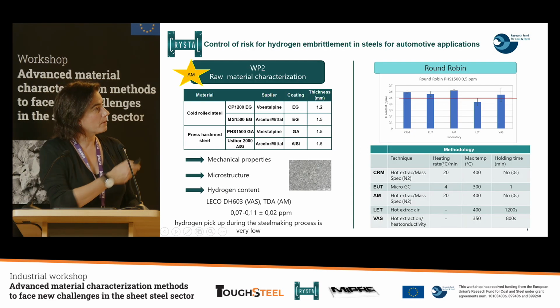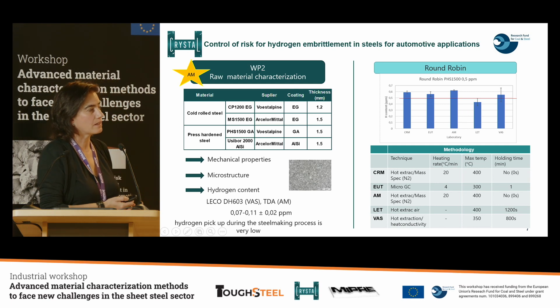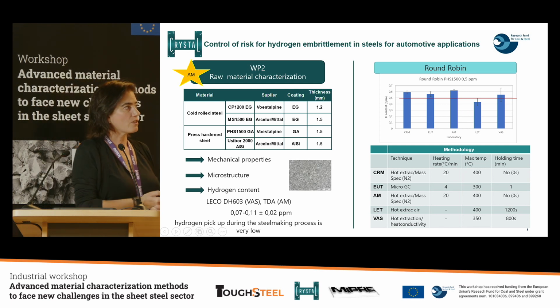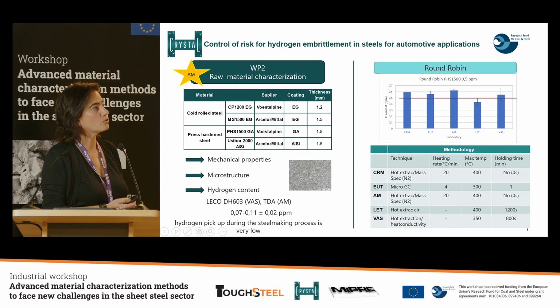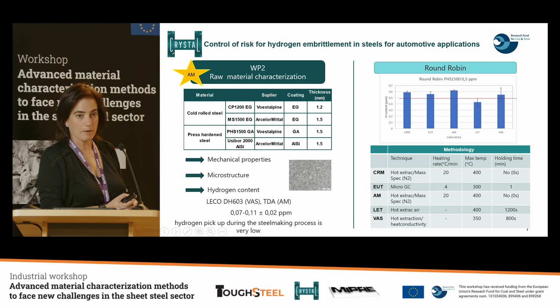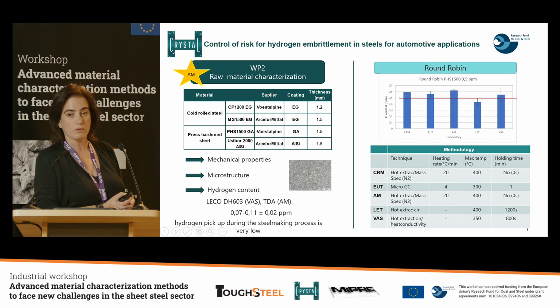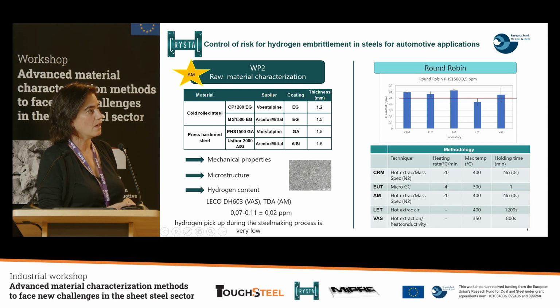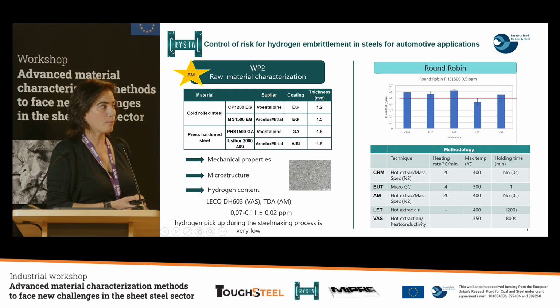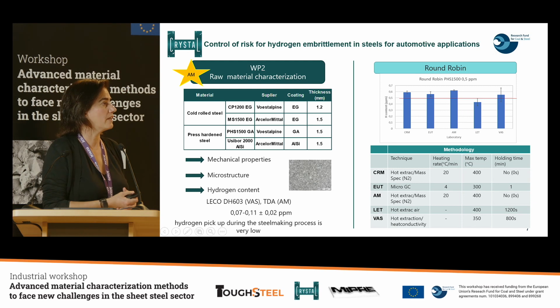So if we move in more detail to all the work packages, and we start with work package 2, we selected 4 steels, 2 cold-rolled steels, in this case CP1200 electrogalvanized from voestalpine, MS1500 also electrogalvanized from ArcelorMittal, and the press-hardened steels were PHS1500 galvanized from voestalpine, Usibor 2000 with aluminum silicon coating from ArcelorMittal. And we performed the same, or the general characterization.